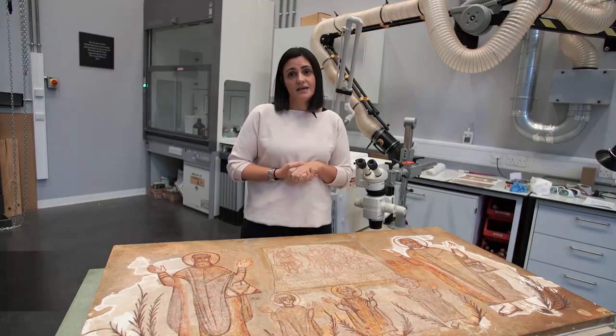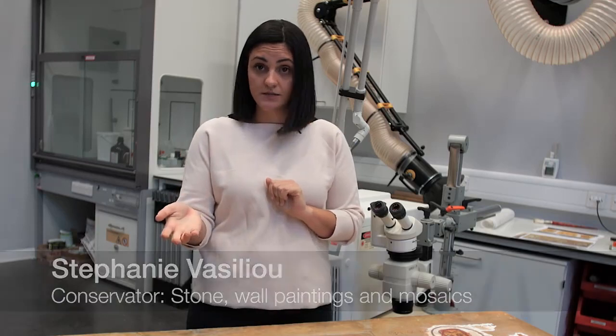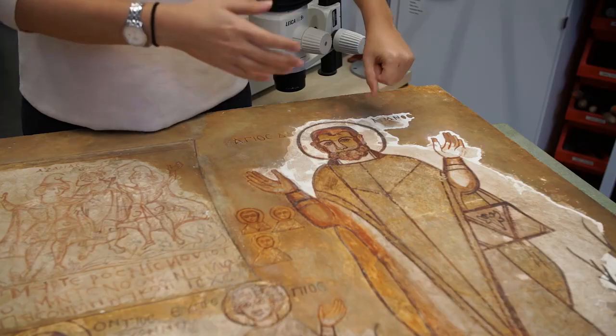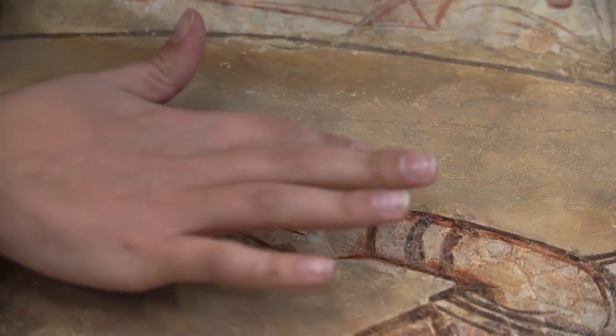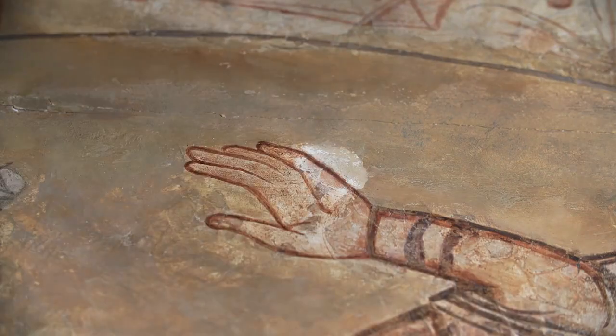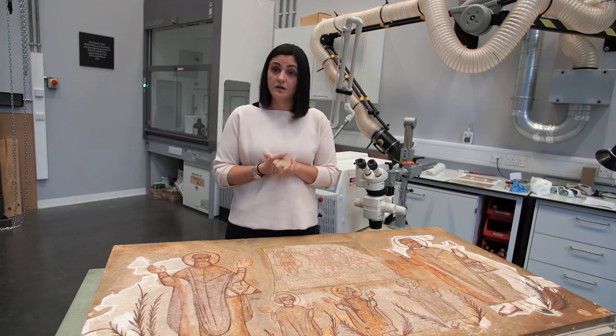I'm Stephanie Vasiliou, a conservator in the Stone, Wall Paintings and Mosaics Conservation Department. After we did the initial poulticing tests, we decided to work alongside science, testing the Erbium YAG laser. The laser has been used quite a lot in the past on easel paintings and mural paintings, so we thought it might be a good machine to try. We did dry testing — a pass with the laser at increasing energies to see what effect we could get. We then also tested it alongside solvents and found that the most effective treatment was a pass with the laser followed by a swab with isopropanol.